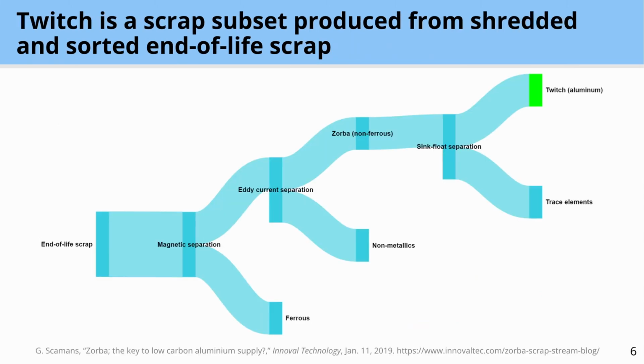So in order to utilize the secondary aluminum, it has to be sorted from mixed end-of-life scrap. First, this mixed end-of-life scrap goes through a variety of different separation techniques, such as magnetic separation and eddy current separation, and this separates out the ferrous and the non-metallic portions of the scrap, which then goes into Zorba, which is known as the non-ferrous portion of the end-of-life scrap, which is further separated via sink float separation into Twitch, which is our aluminum portion of this end-of-life scrap, Zorba, and trace elements such as brass, copper, or zinc.